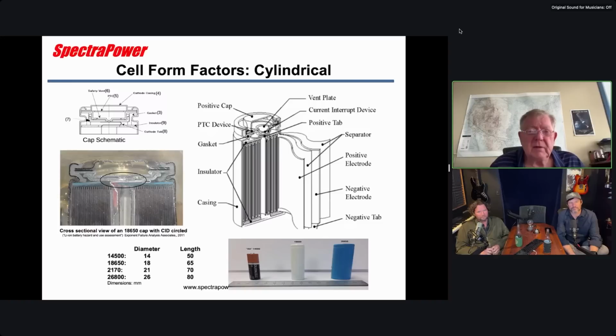And then finally there's a vent. This is what they call a reverse buckling disc. You can see it's usually stamped, and when the pressure gets too high, typically up around 300 to 500 psi, depending on the vent, it'll pop and vent all this gas. If you see videos of an 18650 going off, it'll spray the flammable electrolyte. It'll kind of atomize it into the room, where it mixes with air.